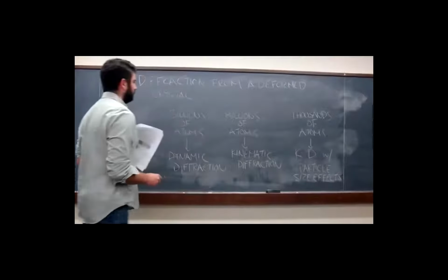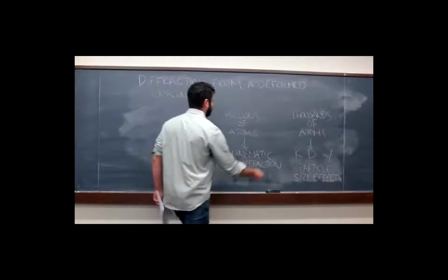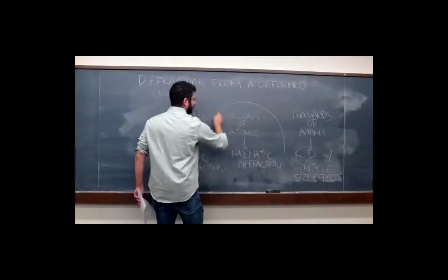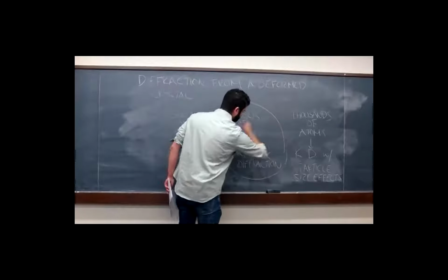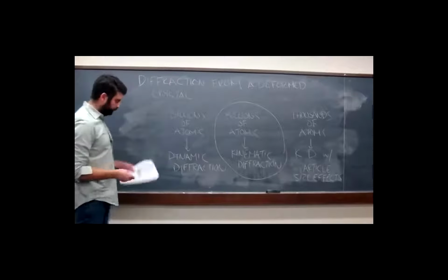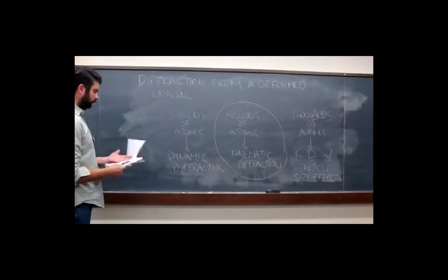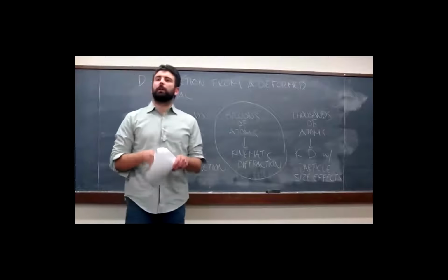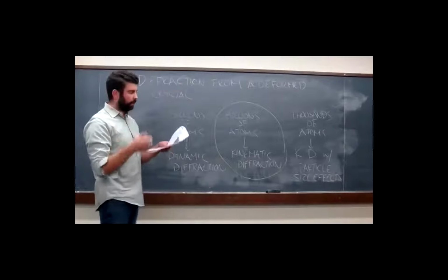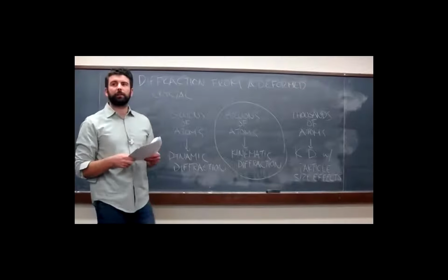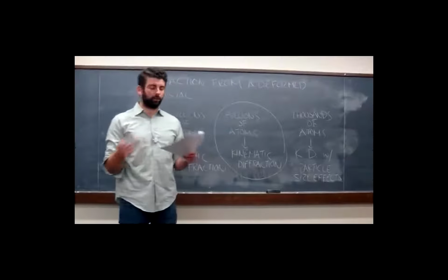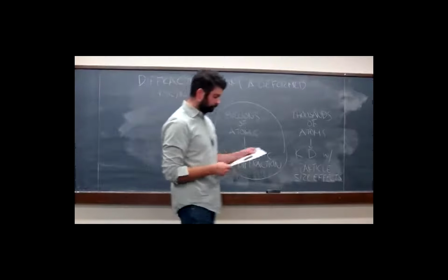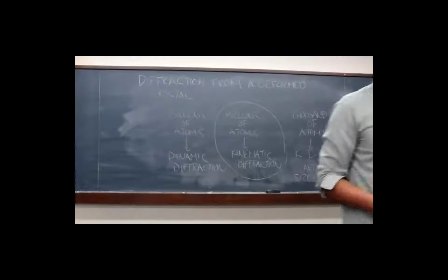What we're going to be using today is kinematic diffraction. And what we're going to do is build up crystals or grains by putting together lots of smaller diffracting units, which we're going to call crystallites or mosaic blocks. This is what's known as a mosaic block model.